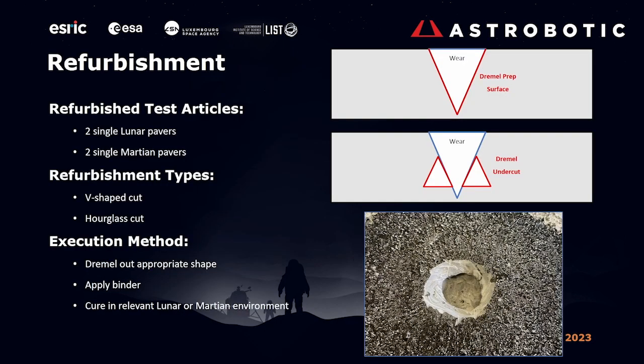And something that we also decided to work on and thought was really important is the refurbishment of these pads. So we talk a lot about landing pad material, sintered landing pads, things like that, but if you need to land on it more than once, you have to be able to refurbish the pad after you've had some amount of damage from the rocket. That's something we see a lot on our vertical takeoff, vertical landing vehicles, where we're landing on a refractory concrete pad out in the desert, but we really have to change our landing location occasionally because we start chewing that material up. So our thought was, well, this is a paste material that we can use to grout between the pavers.